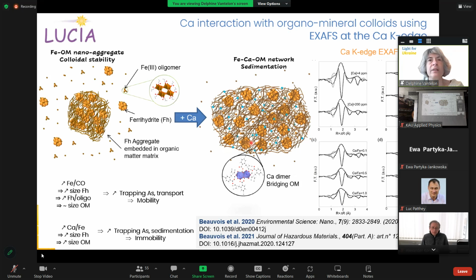And then when calcium bridges the organic matter, you have an increase of the size of the overall colloid that settles. But also you have a liberation of the sites at the surface of the ferrihydrite that can grow a little bit, but also trap more metals, such as arsenic, that has affinity with this ferrihydrite. So in this case, the colloid traps more arsenic and immobilizes it in the sediment of the water system.